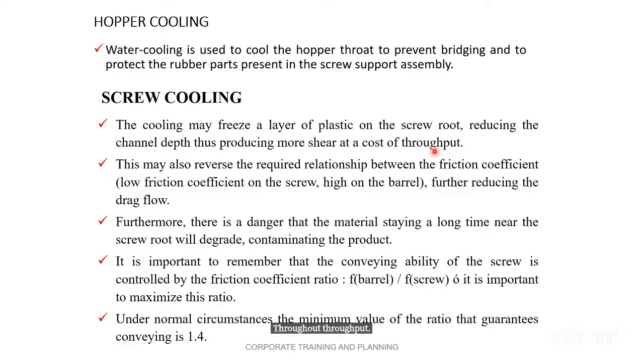I told you, because if you cool the screw, there is higher slippage between the granule and the screw, and that is what we require. Also, this may reverse the required relationship between the friction coefficients: low friction coefficient on the screw, high on the barrel. That is the highest friction between the barrel and the granule, and lower friction between the screw and the granule. Therefore, a high degree of slippage between the granule and the screw, and a low degree of slippage between the barrel and the granules. And therefore, it reduces the drag flow further.